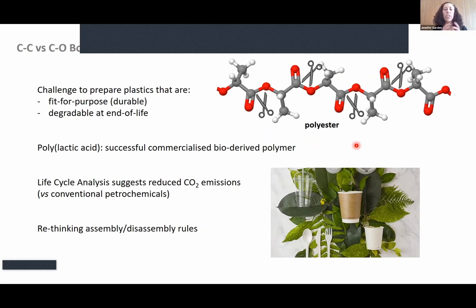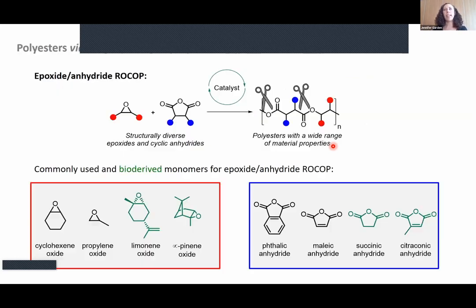We use plastics for such a wide range of different products and processes that it's likely to need a complement of different materials. So as well as polylactic acid as a promising plastic made from renewable feedstocks, then there are other routes to access polyesters with different chemical structures and different properties. So one of these routes is to take an epoxide and an anhydride and to copolymerize these together. And you'll note that we still have these carbon oxygen bonds as the breakpoints in the polymer chain.